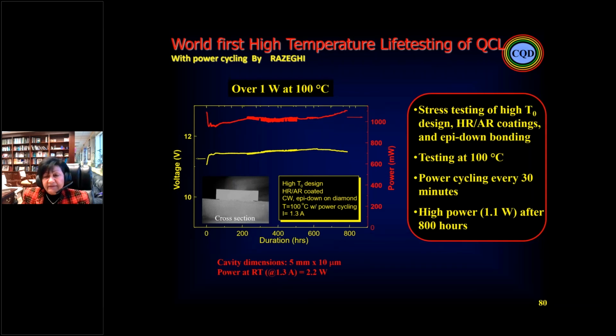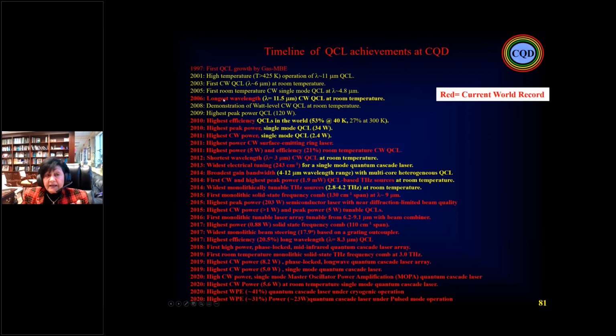So all of the devices that I showed you, without exception, are not only for publication. In the things that I do, the gap between research, development, and production is very narrow. All of these lasers operate at more than 1 watt at 100 degrees C, with power cycling every 30 minutes, and as we can see, there is no degradation. But we need to know the coating, AR coating, HR coating, and so on. Each step is important. And by that, we did the world first in 1997, which was published in Photonics. And up to now, everything that you can see in red is either a first or a record. And that is the future again.